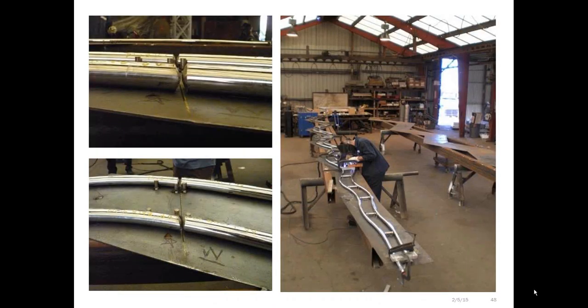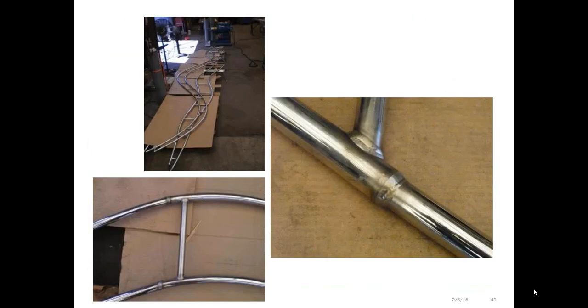So here you go. You see units ready to go, ready to be welded. The tubes on the left were our raw material, before we're into subframes. We have very little space. I think it's probably only a 1/16 of an inch gap between these. It welds fine. It welds nicely. It doesn't move around a lot. Cleanliness, it cleans up nicely. When you see here in the next phase, these welds are done. This is before any cleaning has been done on these welds. There's been no paste, no chemical used on these welds yet, and you can see it welds quite cleanly. These welds will all be fully ground and fully mirrored before the project is completed, but you can see here that it welds and cleans up quite nicely.